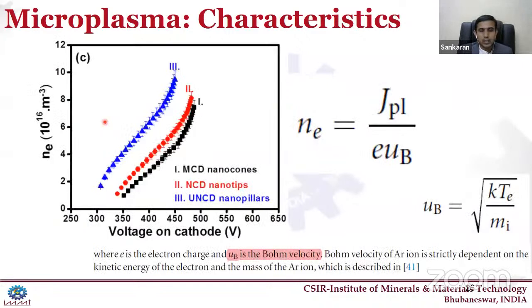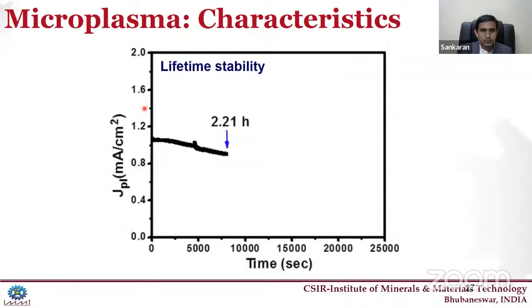So the third is the electron density that we are calculating from the current density values of the plasma. So the density of the plasma is really important, and according to how the density depends, the intensity also increases. So you can see here, with an increase in the voltage, the density also increases, which is parallel to that of the current density values. Next is the lifetime stability.